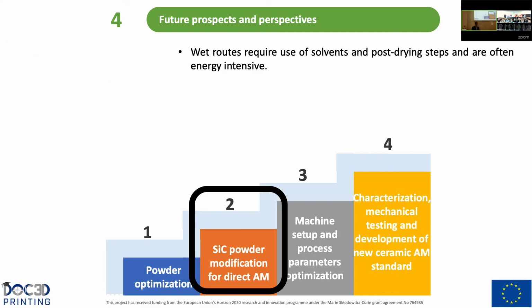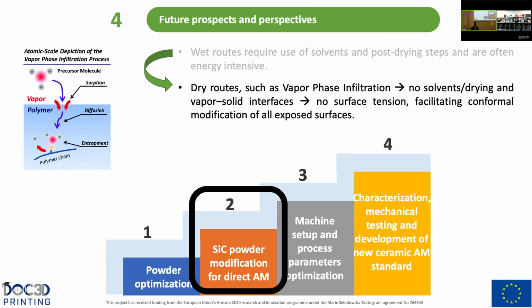Regarding the silicon carbide powder modification, here we are using wet routes, which require the use of solvent and post-drying steps that are often energy intensive. And actually, here we should explore dry routes, such as vapor-phase infiltration, because they don't require the use of solvents or post-drying steps. And actually, this vapor-solid interface has no surface tension, facilitating conformal modification of all exposed surfaces.